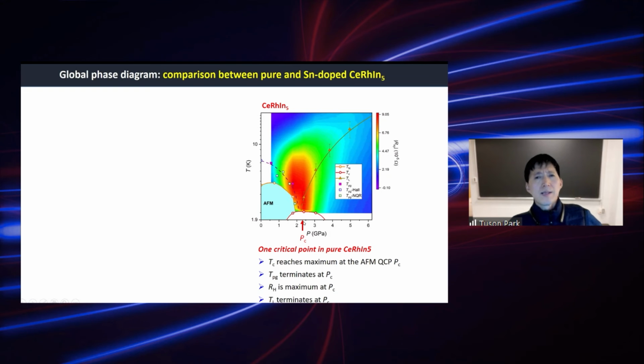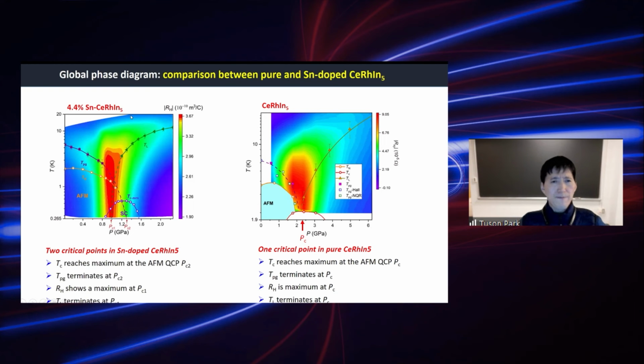So how about the 4.4% tin compound? Okay, so this is a QCP point, and the pseudogap is pretty much gone here. On the other hand, this T sub L, new temperature scale, is here, where the Hall coefficient is maximum. And you can see that the Hall coefficient has a peak, but changes continuously across the QCP point. Okay, so this supports that there is an additional critical point PC1.